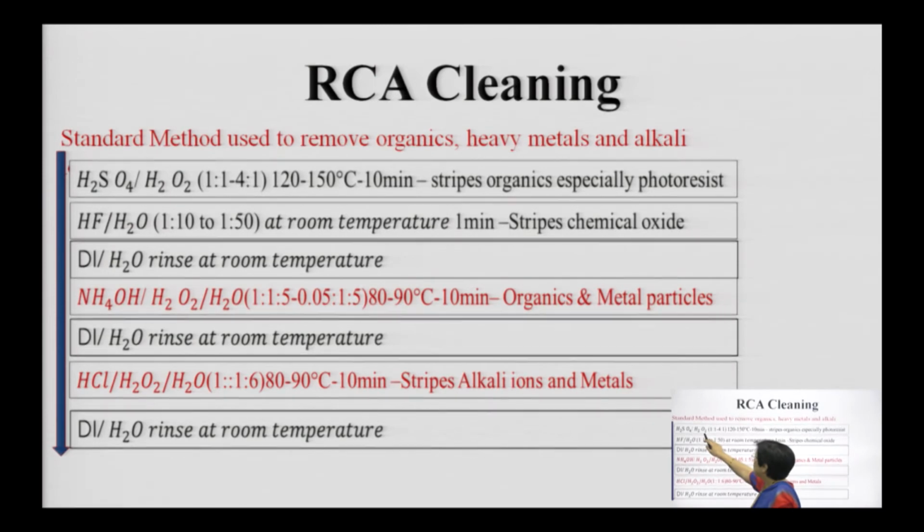First stage is to use H2SO4 and H2O2 for 10 minutes, which is used to strip the photoresist or whatever organics are there. Especially the photoresist and everything will be swept away. Then you are using hydrofluoric acid and H2O. First you are using sulfuric acid and second you are using hydrofluoric acid.